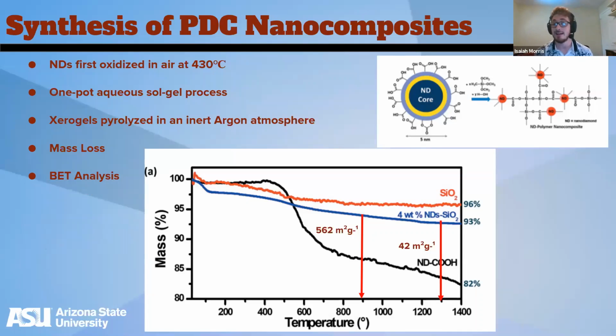So they were first oxidized in air, attaching mainly carboxylic acids to their surface, which then led us to a one-pot aqueous sol-gel process with the likes of tetramethyl orthosilicate, 4 weight percent nanodiamonds, as well as methanol as a co-solvent. Now, upon hydrolysis and condensation in the presence of water, these xerogels were then obtained and pyrolyzed in an argon atmosphere. You can see the results of said experimentation here on the bottom of your screen.